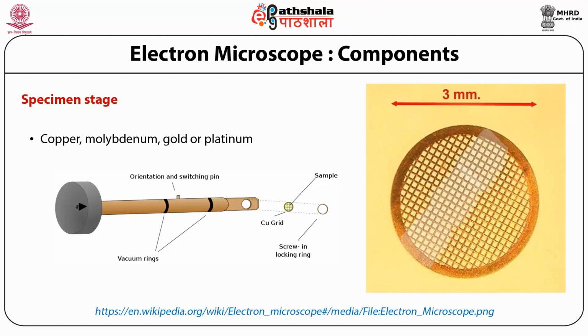The specimen stage looks like this, where we have the vacuum rings. As we know, the inside of the system is vacuum tight, so the sample is put in the grid as shown in this picture, and then these two rings ensure that vacuum is maintained inside. The grid is kept in that stage, and then the stage is pushed under the microscope, in which the electron beam will directly hit the grid containing the sample.